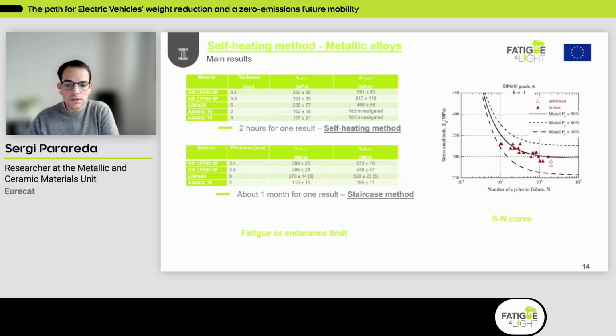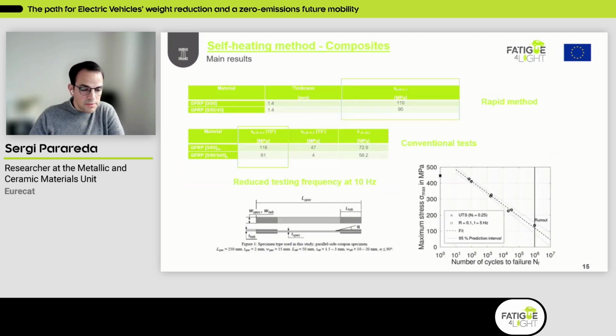And here also, following the same trend, we can obtain the SN curve for these materials by knowing the fatigue limit of the material. We can include 2 or 3 more specimens in this test and get the SN curve in a short period of time. And also these methods were developed for metallic materials, but we also work on developing these methods for composite materials. And here you can see the results for the rapid method and the conventional methods.